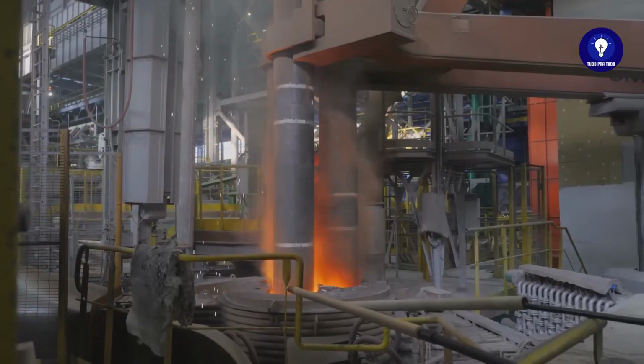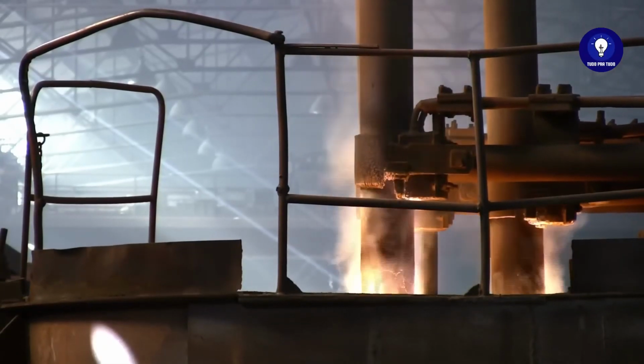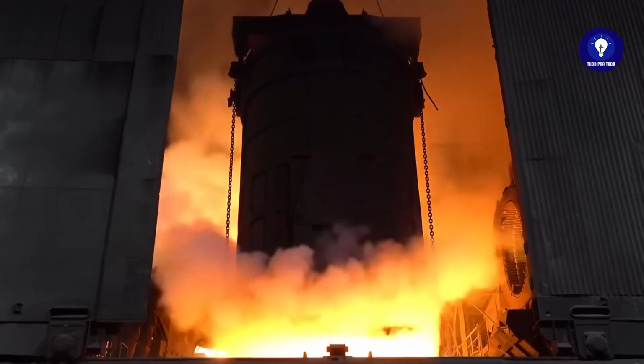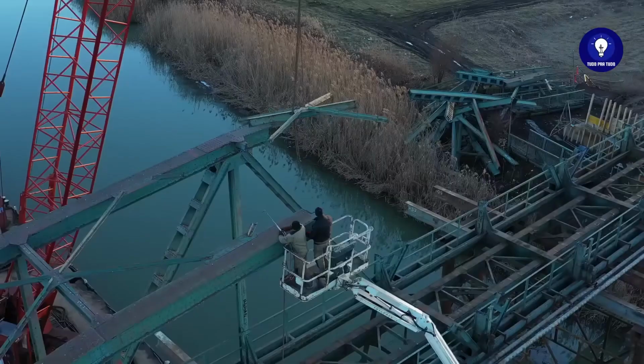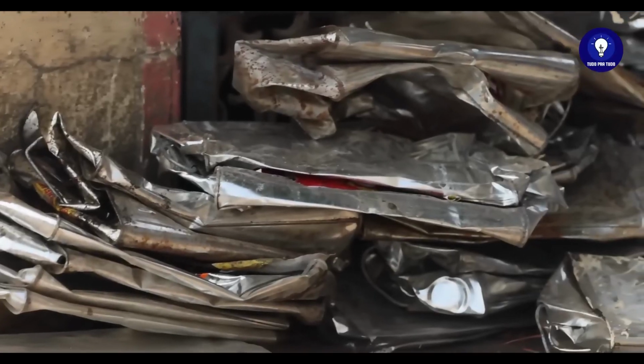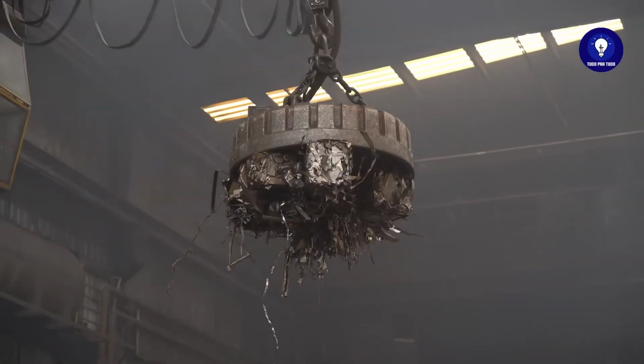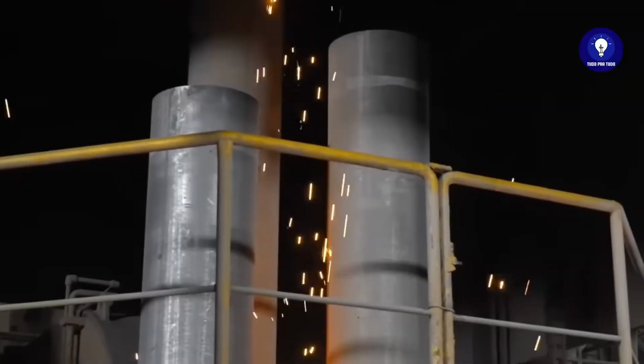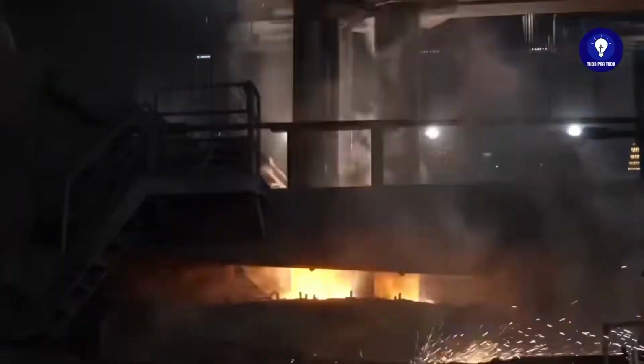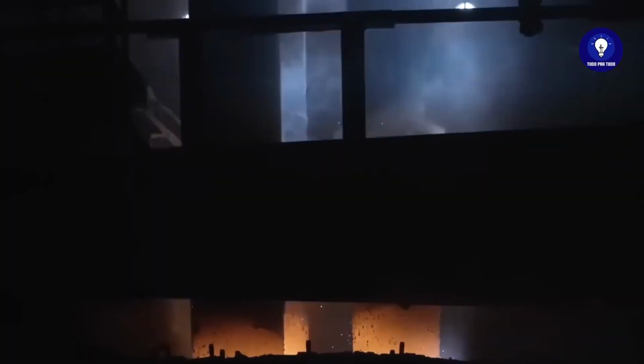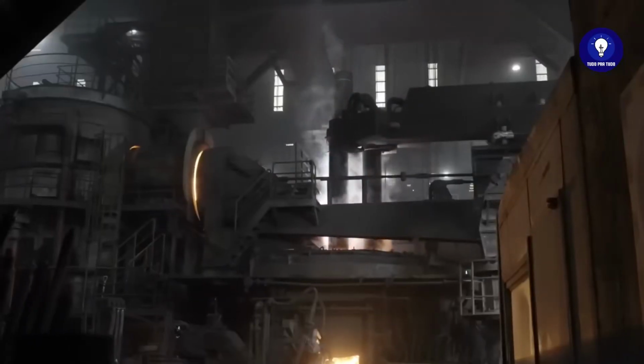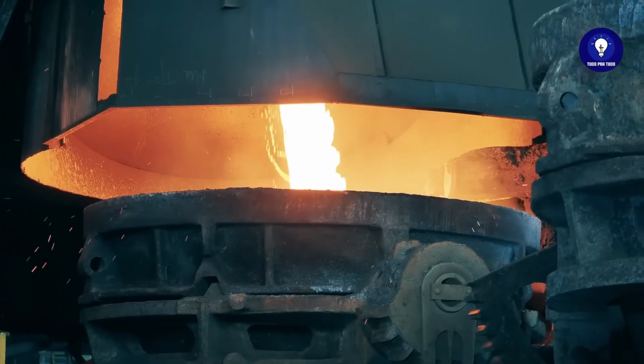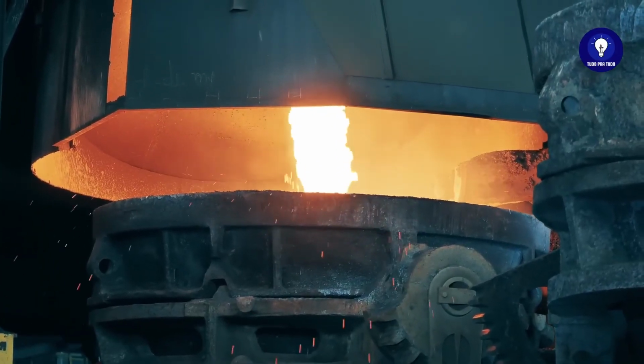However, there is an alternative and increasingly popular route in steel mills to produce steel: the electric arc furnace. In it, the main raw material is scrap metal, beams from demolished buildings, pressed cans, and discarded car engines, which go through magnets, shredders, and equipment for oil removal. Graphite electrodes descend onto the pile of scrap and create electric arcs so bright they resemble lightning. The temperatures exceed 1,000 to 1,700 degrees Celsius, melting everything in a matter of minutes. This method of production doesn't require coke or limestone and allows for the recycling of virtually every steel residue produced by society.